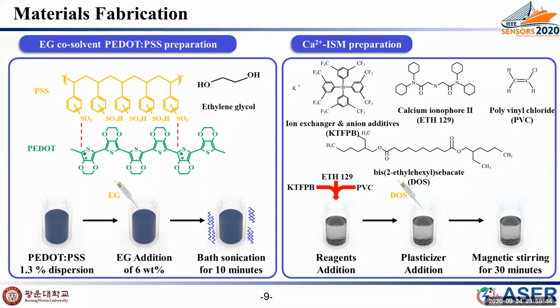From this slide, I explain the total fabrication process. To prepare the transducer layer, ethylene glycol of 6 weight % was added to the PEDOT:PSS water dispersion and sonicated for 10 minutes to achieve a homogeneous solution before use. And then, to prepare the calcium ion-selective membrane, 3 reagents were added to THF solvent, and then plasticizer was added. Then the solution was stirred for 30 minutes.